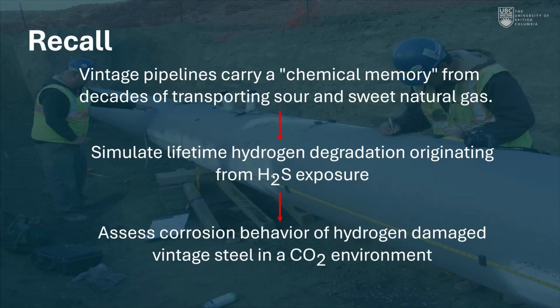So what I did was, as I mentioned, if we recall from a previous slide, we need to look at the memory or the history, the accumulated history of that pipe. And if a lot of these pipes were exposed to sour gas conditions, I wanted to simulate the worst case of hydrogen damage on my vintage steel. And then once I've simulated that hydrogen damage, I take these samples and I expose them to a new CO2-rich environment where I look at the corrosion behavior. So my main goal was to see, how does hydrogen damage affect the corrosion properties in a new CO2-rich environment.